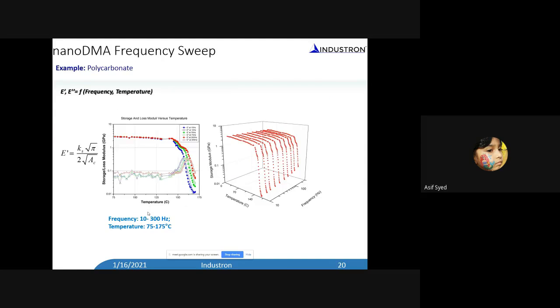Okay, I'm going to show a few examples here. This is a polycarbonate, and I mentioned the dynamic measuring capability, where you apply a sinusoidal force and measure the sinusoidal displacement response and measure the stiffness, the storage component as well as the loss component. From the stiffness, you calculate the storage modulus and loss modulus. That is what is plotted over here as a function of temperature. You can see the storage modulus drop at the glass transition temperature, and also the loss modulus shows a peak during the glass transition, and you can do that as a function of temperature as well as a function of frequency.